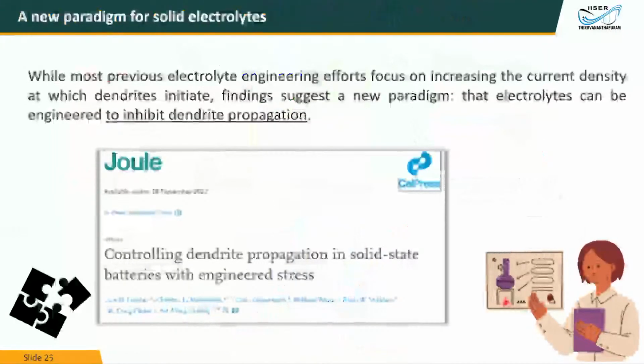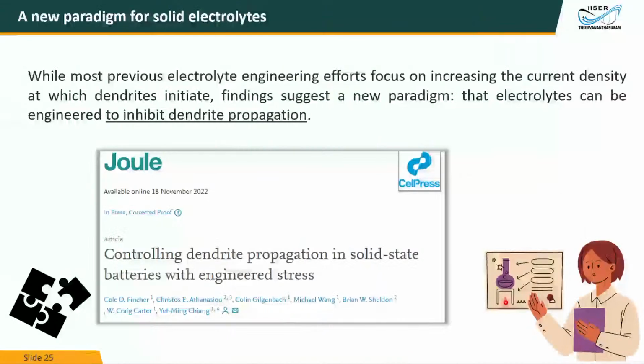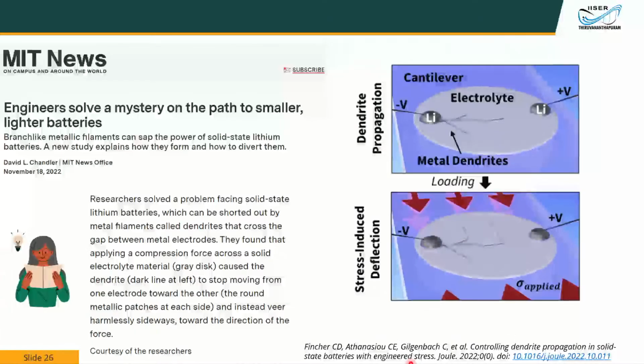And then there is this other one, which is exclusively for physicists, I would say. We have n number of studies that talk about how dendrites grow, and what could be used to prohibit these dendrites. This is one recent article in Joule, wherein they tried to control the dendrite propagation in solid state batteries using stress. So what do you see here? What is this? The pellet, yeah. So you have a pellet here, and then you keep a small patch of lithium over here and over here, and then you start applying potential.